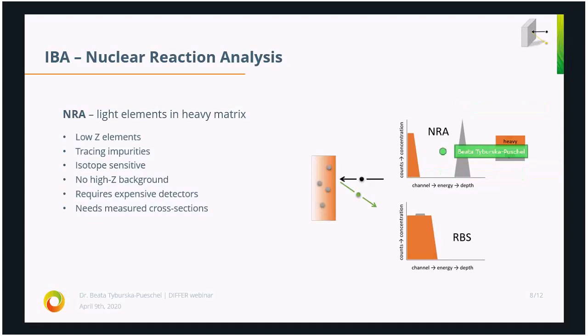And then we have peaks from our light elements. If we would like to perform this experiment using RBS, then our spectrum would be overwhelmed by the signal from the heavy matrix, and we would barely see the signal from the light element. So RBS cannot be used in this case, simply because heavy particles cannot be backscattered from lighter particles. That's the reason why we cannot use RBS in this case.